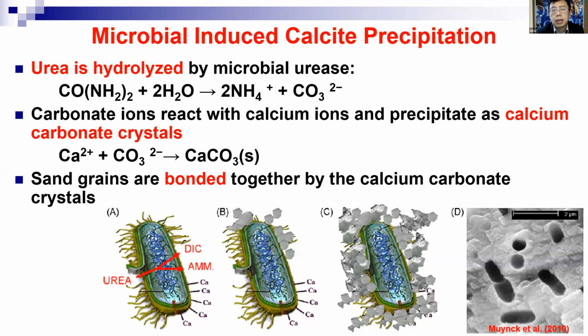The cartoon shows you what the bacteria look like. The bacteria are long-shaped, and the surrounding surface has a negative charge, so they can attract calcium ions around them. When the urea is hydrolyzed by this bacteria, it releases carbonate ions. It also changes the pH environment, favoring alkaline conditions, with the pH higher, close to 9 or 10. So that favors the precipitation. We can see here that when they precipitate, it happens surrounding the bacteria.